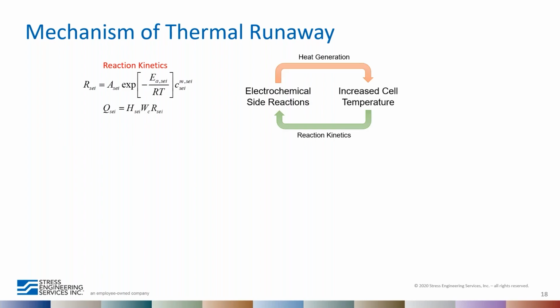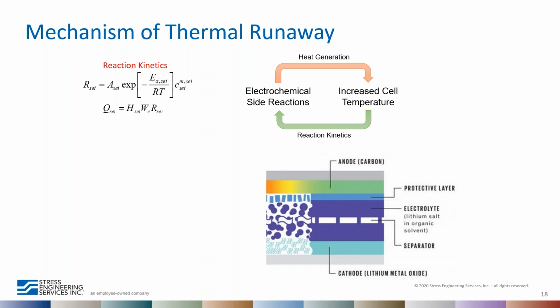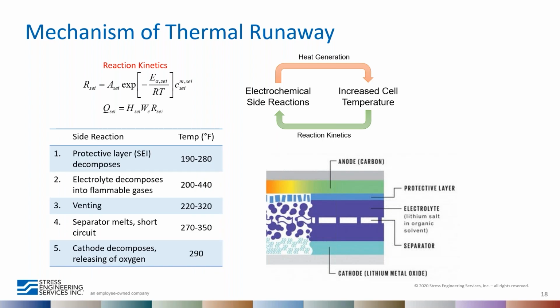So what is thermal runaway and what causes it? I mentioned that there is this feedback loop between side reactions and increased cell temperature that really drives the runaway behavior. This happens throughout the cell in the different components. Each has its own decomposition reaction that has a characteristic heat output and onset temperature range. In general, the accepted pathway is as follows. There's a protective layer that forms between the active material and the electrolyte called the SEI. That starts to decompose at a fairly low temperature. And then the heat from that reaction feeds into the electrolyte decomposition and flashing.